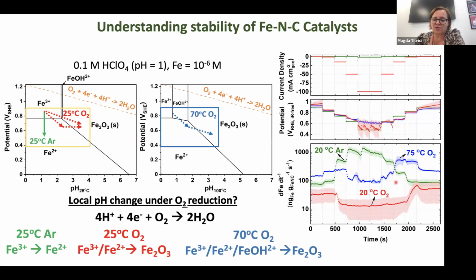I just wanted to tell you that basically what happens really under oxygen is that your single atom catalysts come together, they precipitate as iron oxide, some of them leak into solution, and some of them reprecipitate back on the catalyst. When you are at 70 degrees, your iron single sites change to iron oxides that might reprecipitate on your catalyst and then leak back into the solution. And we can monitor the concentration of iron in the solution constantly under different potentials or current densities.